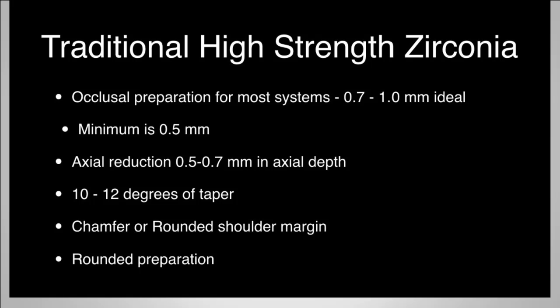Now with traditional high-strength zirconias, our occlusal preparation can be close to 0.7 to 1 millimeter. Again, 0.5 is a minimum thickness. I would recommend not getting that thin. Again, if you have to adjust, you may drastically weaken the overall structure. We need an actual reduction of 0.5 to 0.7. I'm comfortable with that with the traditional materials. We do need a more tapered preparation. That taper should be on the order of 10 to 12 degrees. A rounded shoulder margin or a chamfer margin is acceptable. The preparations must be rounded.